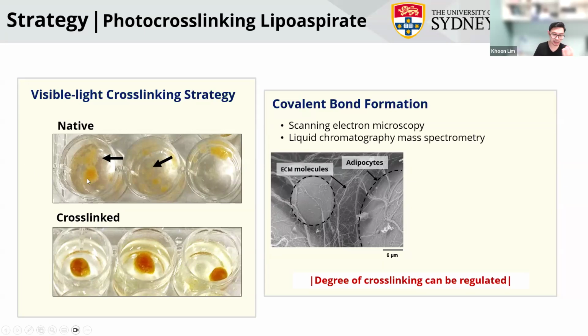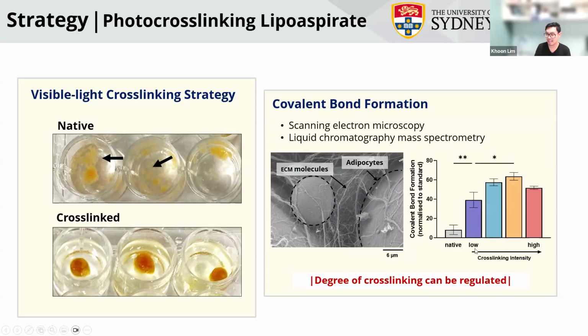So you can see here, if you take native fat and then you culture them in media or in water, they will start floating to the top, and then they have no shape on them. But if you take them, mix them with our photo initiators, and then cross-link them, you can see much better preservation of this shape. And we look at the formation of these covalent bonds. We look at how the adipocytes within them and the ECM molecules respond, if this cross-linking method is going to affect the adipocytes, we don't see any negative phenotypic changes. But what we also did see is that increasing our photo initiator concentration increases the covalent bond formation in the native lipoaspirate extracellular matrix.